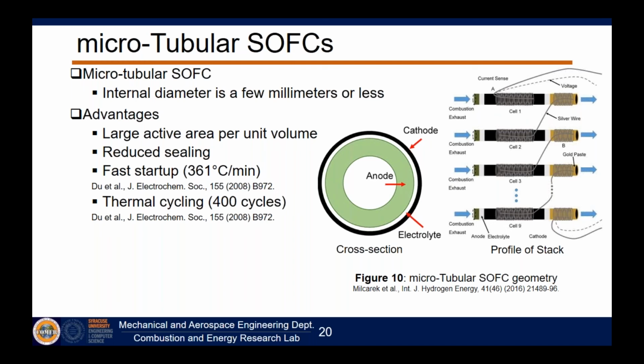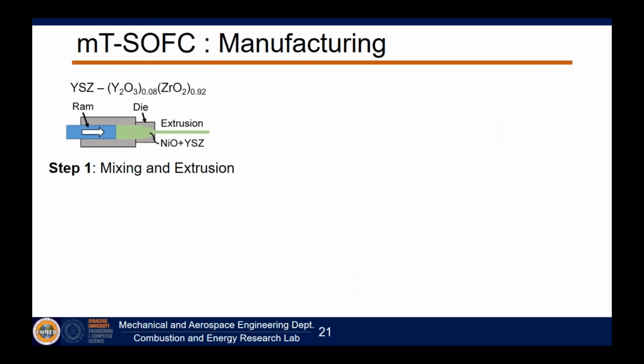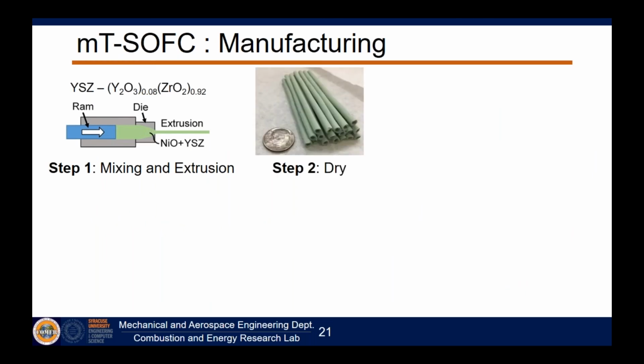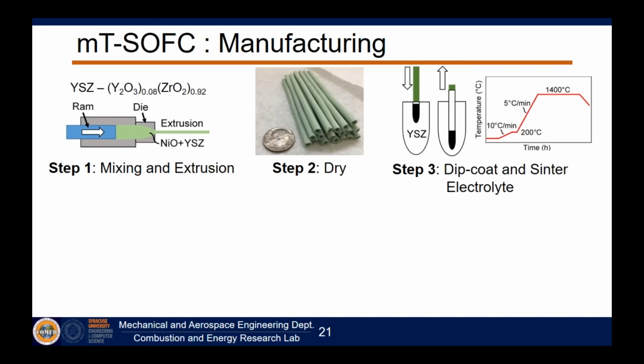We started developing those. To develop them, we go through an extrusion process. You probably had an extruder if you played with Play-Doh before, right? You push the Play-Doh through and it goes through this die. It ultimately forms this tube shape, which is here. This gives you a sense of what it looks like. Here's a dime for comparison. We then take the tube and we dip it in this slurry. It's a liquid that's very viscous, essentially. And this is our electrolyte material with some other additives.